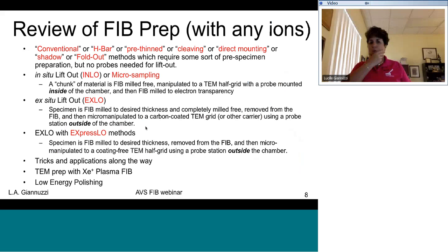All right, so what we're going to talk about first is conventional or H-bar pre-thin or cleaving, and direct mounting. These are basically different ways to FIB mill a sample that is already pre-mounted on a TEM grid or somehow mounted on a TEM grid. And this can be done with gallium or xenon or basically any ion that you have. Then we're going to talk about in-situ lift-out, ex-situ lift-out, and some new methods that I've been working on. I'm going to show you some tricks and applications along the way, specifically TEM prep with xenon plasma FIB and low energy polishing.